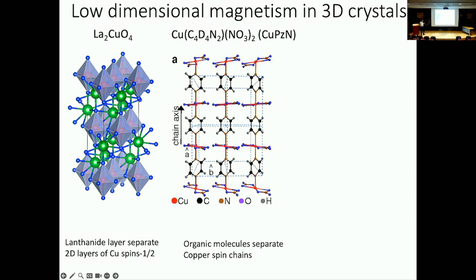Now, why is it one-dimensional? It's because electrons, in this case, can only hop through these pyrazine rings. And so these are my magnetic atoms, the copper atoms, but the hole, if you will, from the 3d9 configuration can only hop through this ring, and so can only move in this direction, whereas it's quite difficult to have hopping take place between the chains, and therefore we get very, very weak interactions. Not zero, there is always some degree of interaction, but really very weak interactions between the chains.